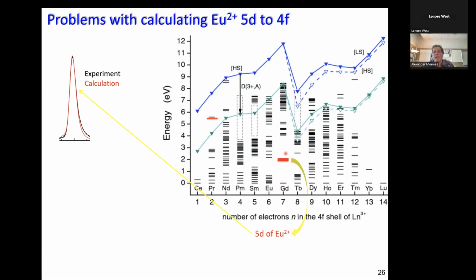The point is now, where do the 5D orbitals reside? And I show this here in gadolinium and in europium 2+, they reside here. That is the reason when you populate 5D and it decays, it can only decay to the ground state. So I would go out on a limb and say the really only relevant materials today with modern LEDs are two elements, europium 2+ and cerium 3+. The reason is only there do you get clear emission from 5D to 4F.